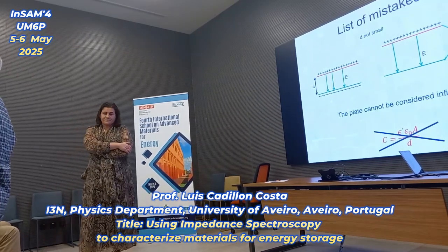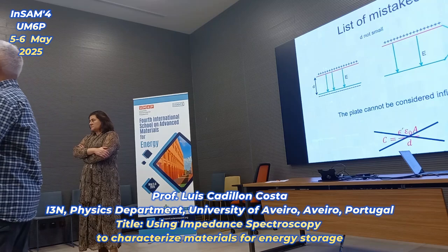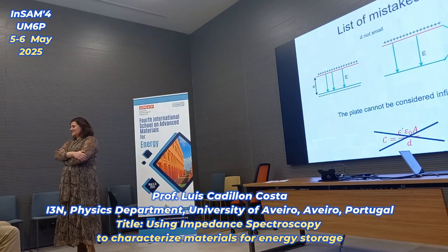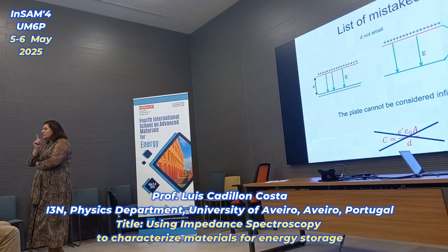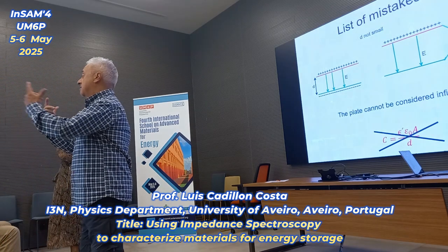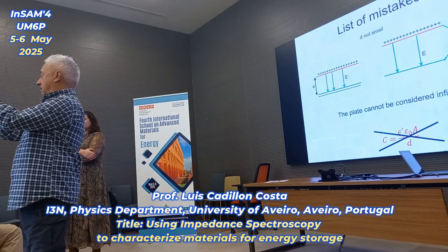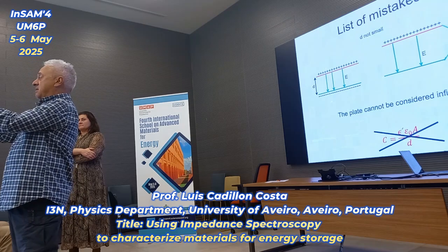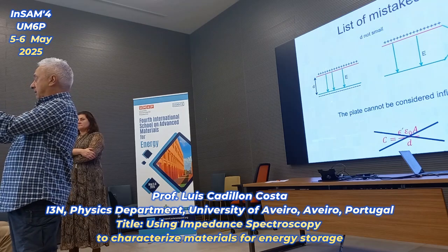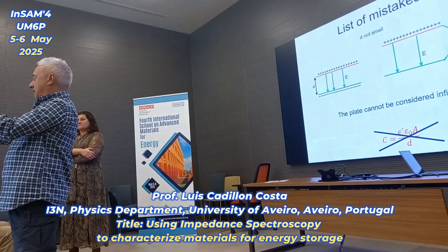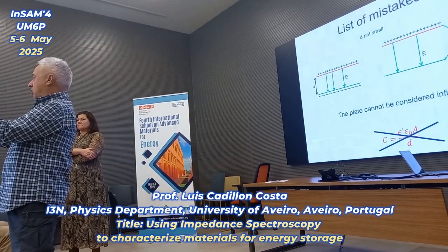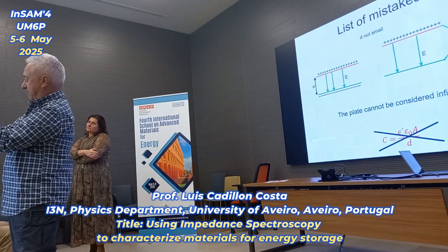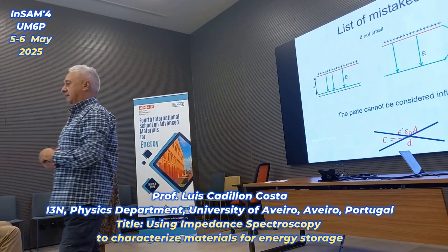It's impedance spectroscopy. Right now they're using the Debye model. But the model usually is not Debye, for sure. It's rare. Because the problem with the Debye model is that you have dipoles that relax exponentially. This means that this dipole does not interact with this dipole. This dipole does not see these dipoles. In most materials, they are connected some way. So when this one turns, it affects this one, and so we have no more Debye. We have a distribution.